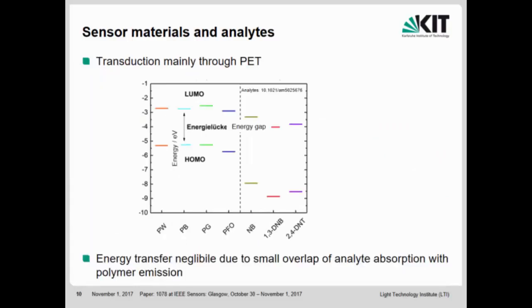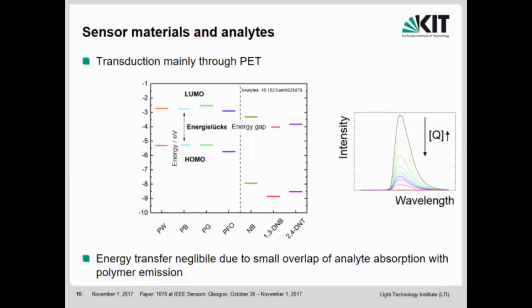To see if this will work in principle, you'll need to measure the HOMO and LUMO levels of the different materials. So in this case, we use the materials called polymer white, polymer blue, polymer green, and PFO. The first ones are PPV-based materials from Merck, which have a slight change in the side groups, which make them emit white, blue, or green, and the PFO materials. And here are the analytes that we are aiming for: nitrobenzene, dinitrobenzene, and dinitrotoluene. There you can see the HOMO and LUMO levels of these materials, and you see that you have a possible electron transfer.